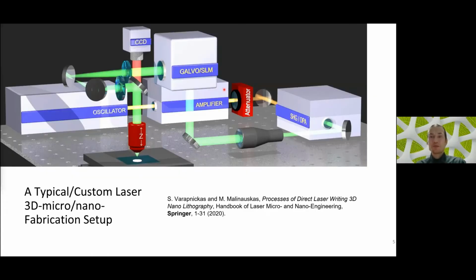Okay, so just to get back to the ground, or deeper into the lab, the typical setup will consist of a short pulsed laser source, whether it would be an oscillator or combined with an amplifier, which is typically not a necessity for single beam two-photon polymerization, but it can be useful for some purposes. In any case, we'll need power attenuation to precisely control the power, corresponding to intensity at the sample, if needed, and having the possibility that the light wavelength can be tuned or changed, and the beam can be deflected by a galvo scanner or translated by stages.